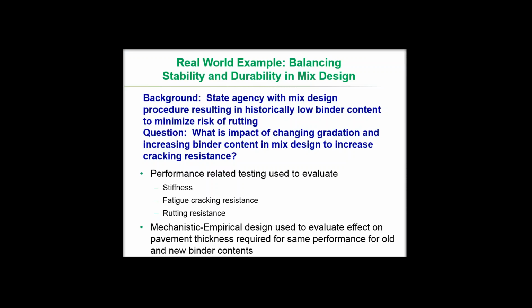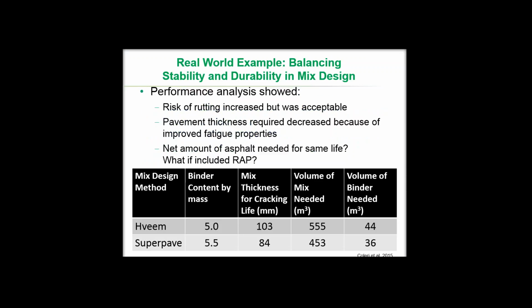And then mechanistic empirical design was used to evaluate the effect on the pavement thickness required for the same performance for the lower binder content under the old mix design system, or with a somewhat higher binder content under the new mix design specifications. And the result was that the risk of rutting was increased, but it was way over-specified previously, and the risk of rutting was still acceptable with the increased binder content in general.